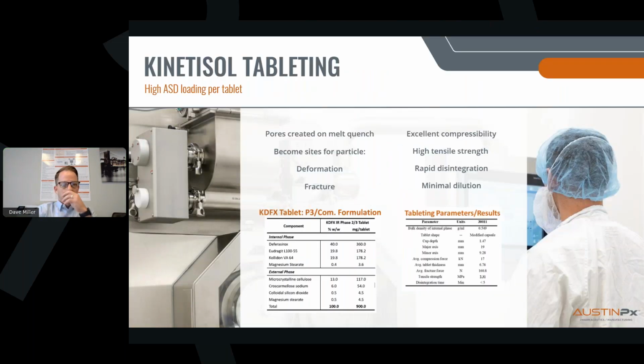So a little bit more on tableting insights with KinetiSol. KinetiSol produces, as I said, highly compressible porous particles that really behave beautifully in direct compression. The micropores that are created during the rapid melt quench step of the KinetiSol process become natural sites for particle deformation and fracture under compression.